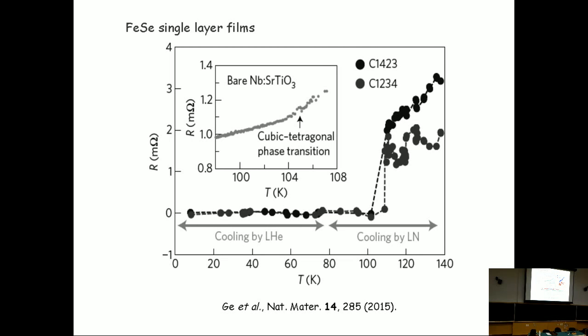most interestingly, superconductivity can go to very high temperatures under certain special conditions, for instance applied pressure. In this particular case where the maximum transition temperature was found, we can potentialize superconductivity by strain. In this case you have a single layer of iron selenium deposited over a strontium titanate substrate doped with niobium, and you have just the right strain in the plane, in the layer, to optimize the Tc, and in this case the Tc goes up to above 100 Kelvin. So that's pretty much, as far as I know, the maximum Tc that has been found in this type of materials, and that's comparable to the cuprates. So it's a very strong Tc.